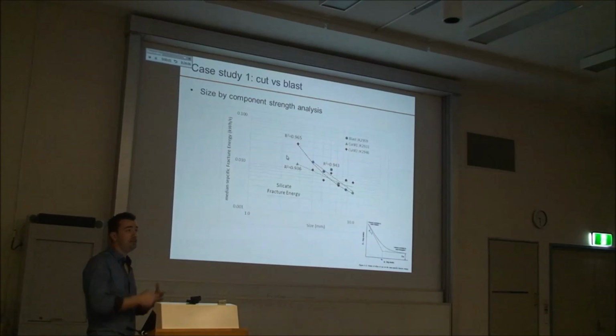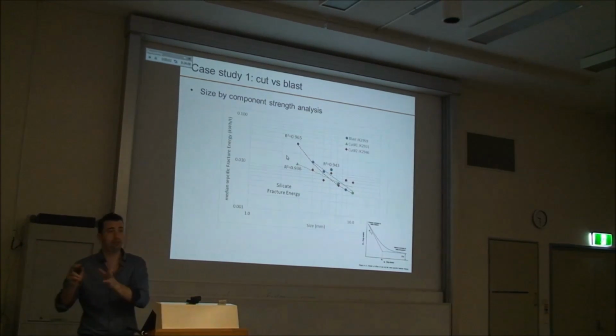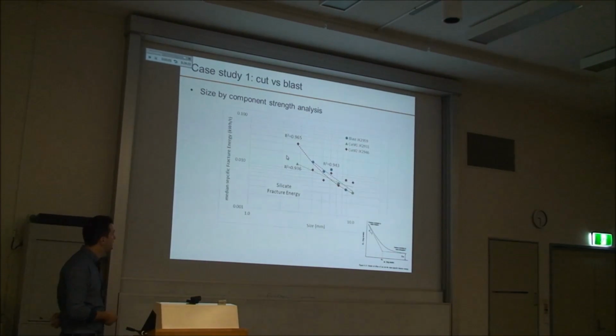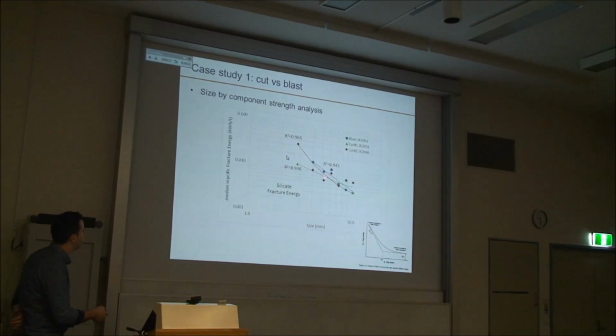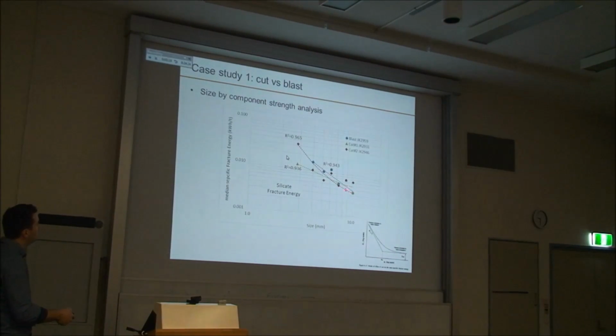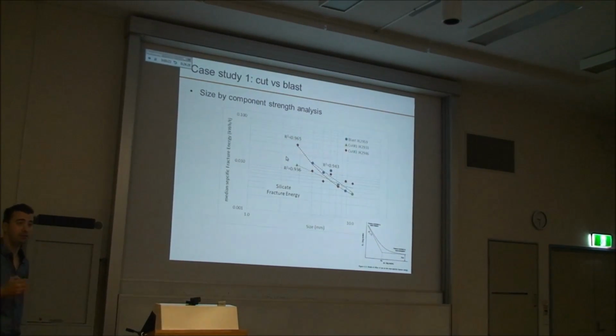So I went on and did the test on the cut rock and the blast rock. This is the curve here plotted for only a very narrow size fraction. So what I'm looking at here is only a tiny little bit of this curve, but this is enough for this test. And what was found is that there is no significant difference between the cut and the blast product. They have roughly the same strength properties.